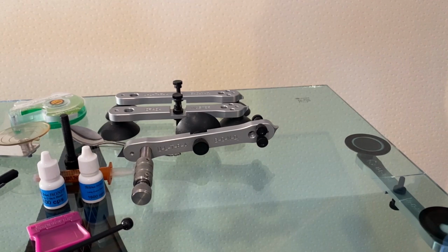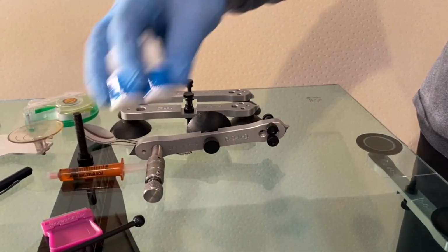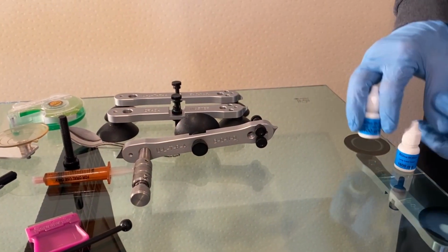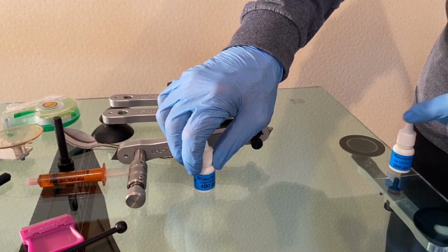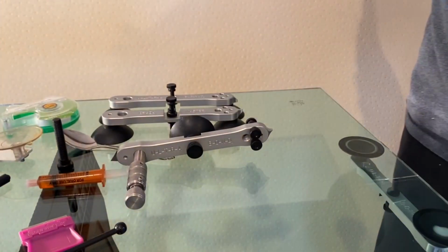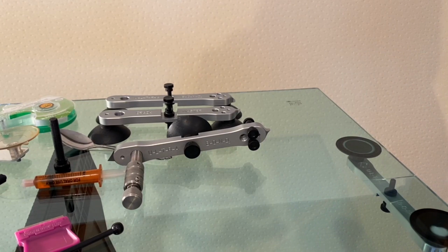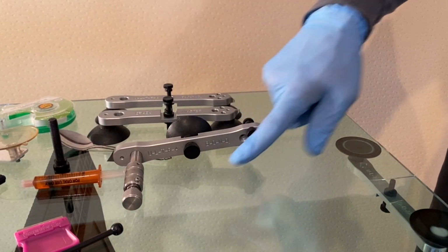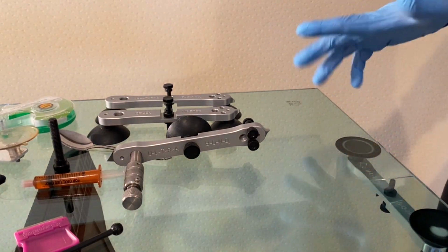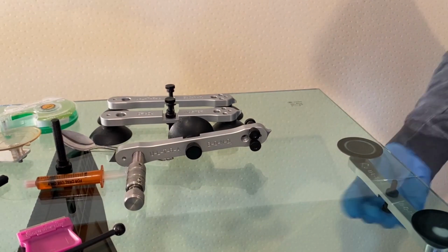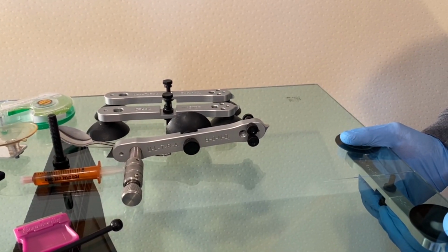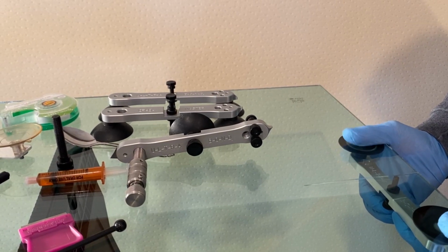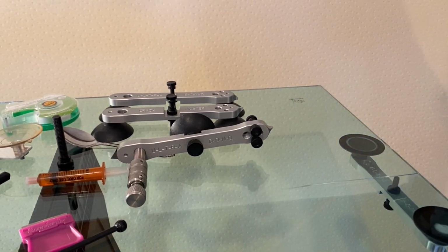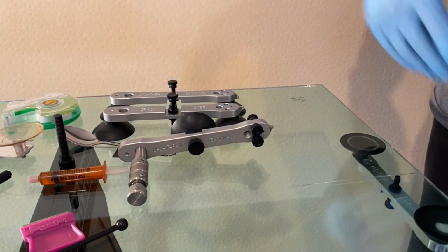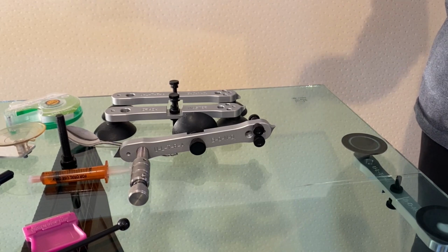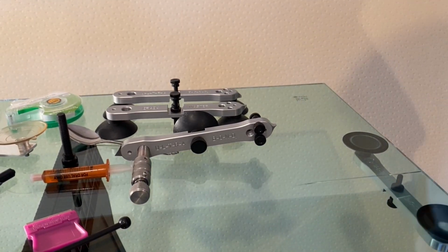Now in the real world, when you fix an edge crack, you're going to use either our 1600 CPS resin at the edge and our 400 at the point. While you're practicing at home, just to get your moves down, you're going to use 45 in the point and 90 at the edge. So now let's see if we can spread this crack out a little more. Let's see how long we have to make sure it is over 6 inches, because 6 inches is a dirty word in this industry. So I believe we have about 8 inches here.